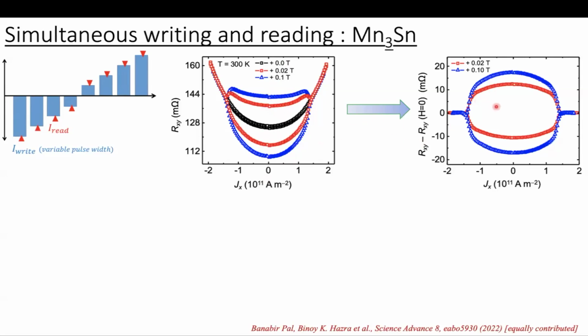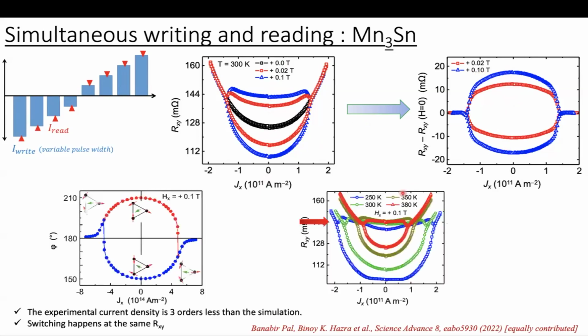And when we correct from the zero field, we see here as well nearly 40% switching for 0.1 Tesla. Theoretically it has also been calculated. We observe a similar profile and it matches quite well. The only difference is that experimentally the current density is 10^11 ampere per meter square, whereas theoretically we need 10^14 ampere per meter square. So from this we can see heat also plays a role in the current induced switching experiment, and it can be explained using conventional spin orbit torque.